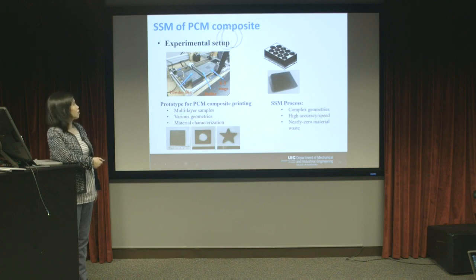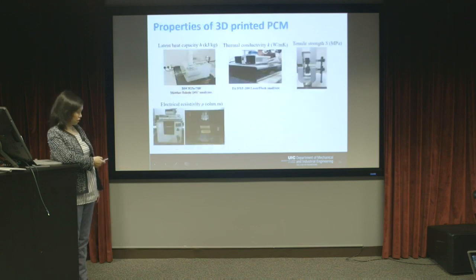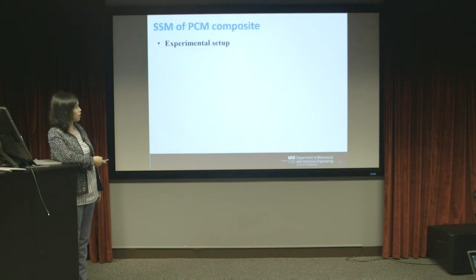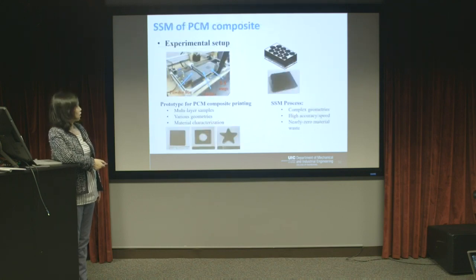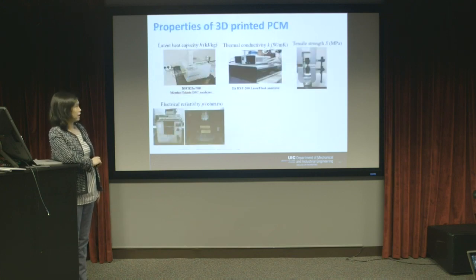So this additive manufacturing process is okay. It can fabricate complex geometries, and it can achieve high accuracy and speed and almost nearly zero material waste. But there are still some problems. A big issue here is the binding between the graphite powder and the paraffin wax powder, because you melt the paraffin wax powder to bind the expanded graphite powders together. So when it's heated, the binding is kind of loose. So it will have some leaking issue.